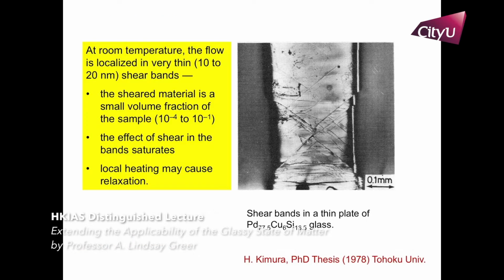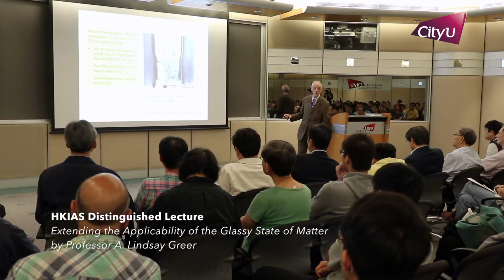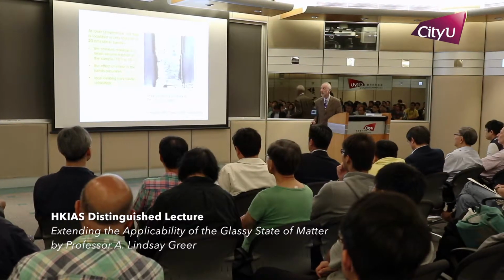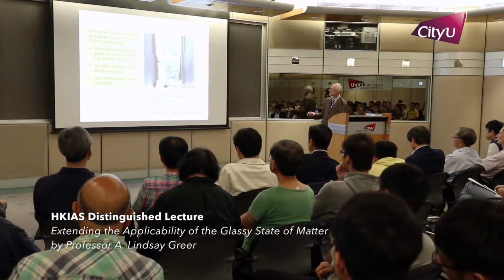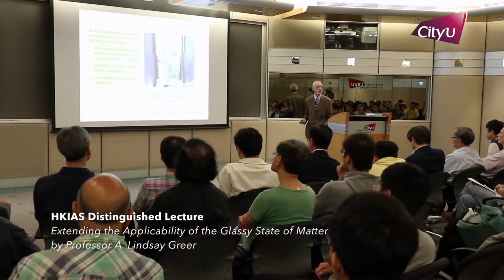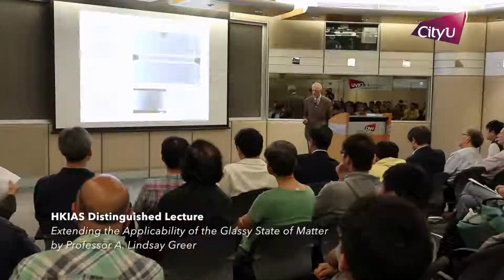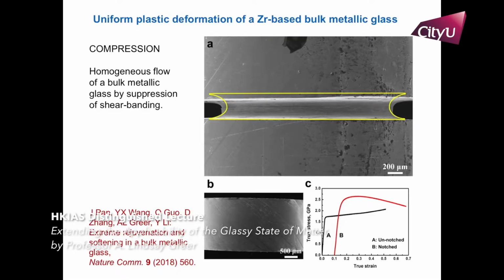Well, it's actually because of these shear bands, which have been studied for a very long time, back to the earliest days of metallic glass studies. So you deform this material, but the deformation is all focused in these thin planes. The stored energy there undoubtedly will saturate in some way, and then you get local heating that will relax that stored energy away also. So this is a very inefficient pattern if you're going to store energy in the system. Could you make it more efficient?